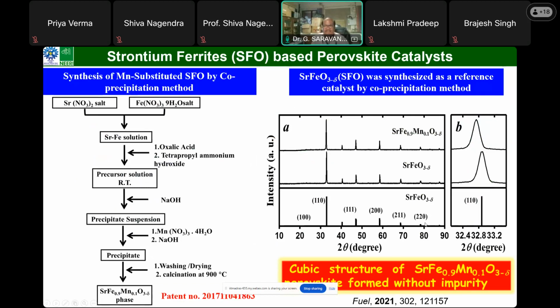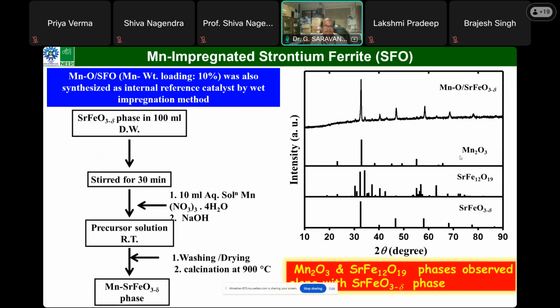So generally after synthesis, we perform XRD to check whether the synthesized material is stable or not. And this is the unsubstituted one. When we substitute the manganese in the lattice of strontium ferrite, the diffraction peak is shifted to a lower angle. That means the lattice has expanded while incorporating manganese.